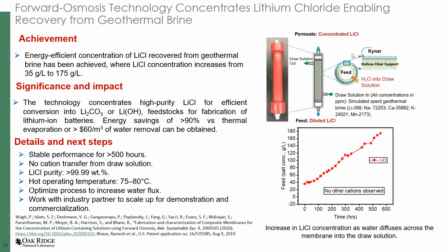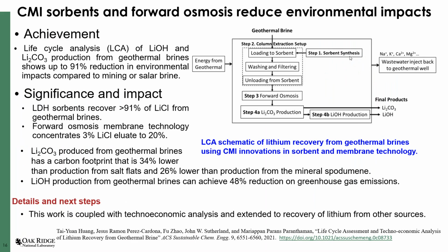We have done both life cycle analysis and techno-economic analysis. We combine the use of LDH with forward osmosis, then finally lithium carbonate or lithium hydroxide production. It shows lithium carbonate can be produced with a carbon footprint 34% lower than the salt flats, and 26% lower than production from spodumene. So it's going to be a really economical process. It can also achieve a 48% reduction in greenhouse gas emissions. So we published again.